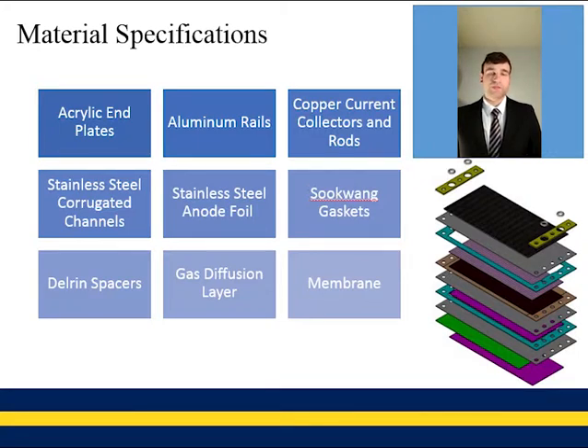As for our spacers, we chose Delrin because Delrin is a polymer, and polymers are low conductors and they're resistant to heat, corrosion, and are structurally stable. Our gas diffusion layer is one of the most important parts of the cell. So we chose a material that was hydrophilic, which allows passage of heat and water removal. So we chose carbon papers as our diffusion media. Lastly, our membrane has to be a semi-permeable material, allowing the flow of protons while keeping gas and hydrogen out. So we chose a strong ionomer as our membrane layer.